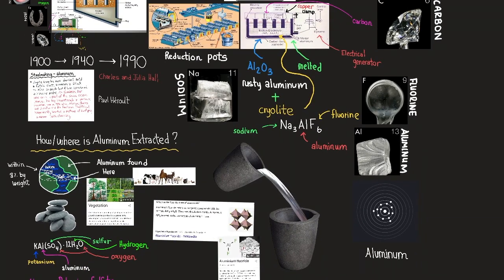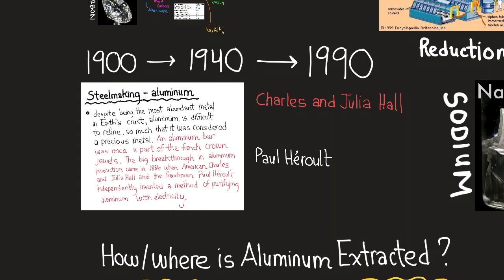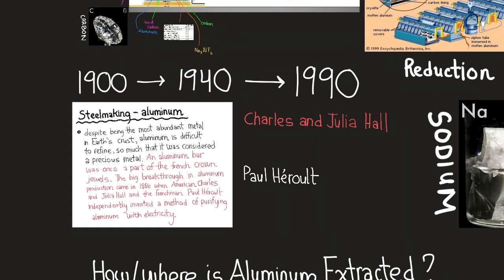So continuing on, molten aluminum is siphoned from cells in large crucibles. From there, the metal may be poured directly into molds to produce foundry ingot. It may be transferred to holding furnaces for further refining or for alloying with other metals or both to form fabricating ingot. As it comes from the cell, primary aluminum is about 99.8% pure. Automation and computer control have a marked effect on smelter operations. The most modern reduction facilities use fully mechanized carbon plants and computer control for monitoring and automating pot line operations.